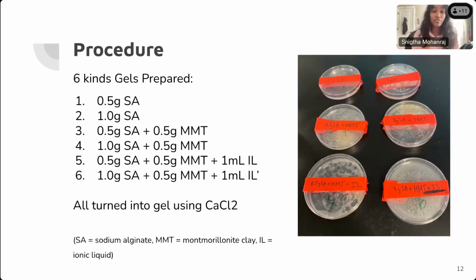The first 2 were 0.5 gram and 1.0 gram pure sodium alginate, and I did this alternation between 0.5 and 1.0 to see how that affected results. So then for the next 2, I added the montmorillonite clay, or MMT for short. And then for the last 2, I had the MMT as well as the ionic liquid, or IL for short. And these were all turned into the gel polymers through using calcium chloride.